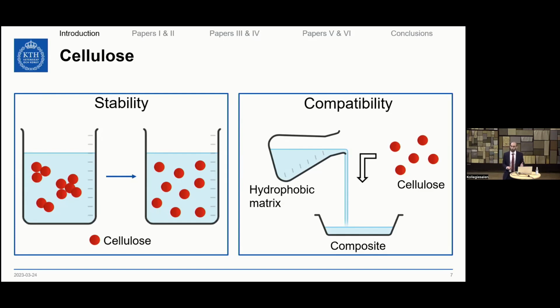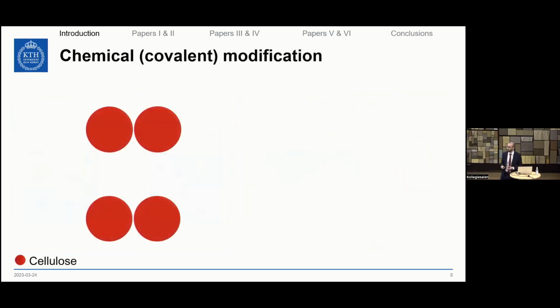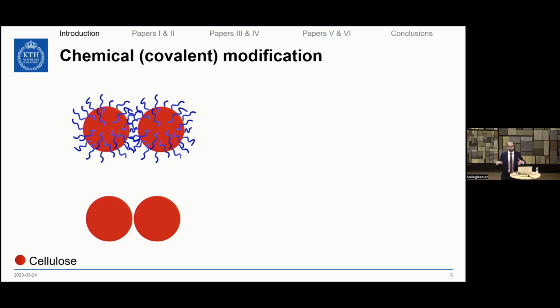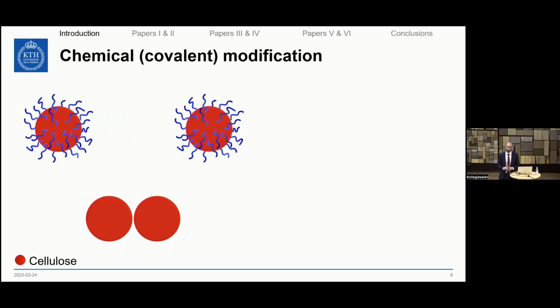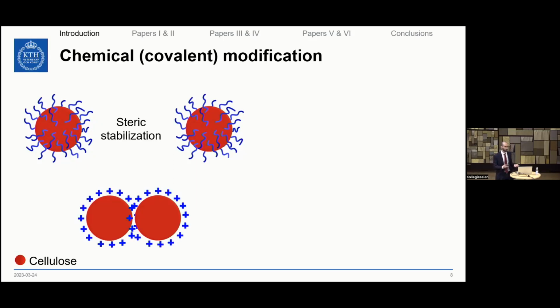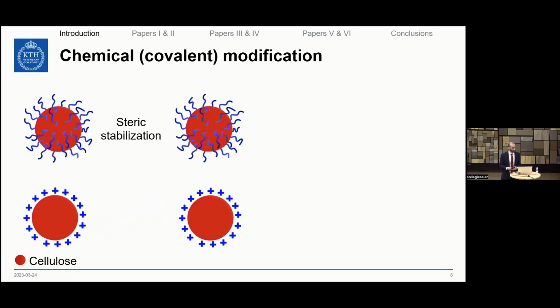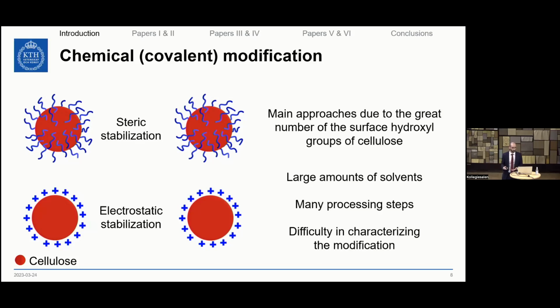There are many ways in order to approach this. One way is to use chemical or covalent modification techniques, where we can have the grafting of polymeric chains on the surface of cellulose, which will force cellulose molecules further apart from each other through steric stabilization, or we can introduce charges on the surface of cellulose, which will have the same effect as steric stabilization, but this time through electrostatics.